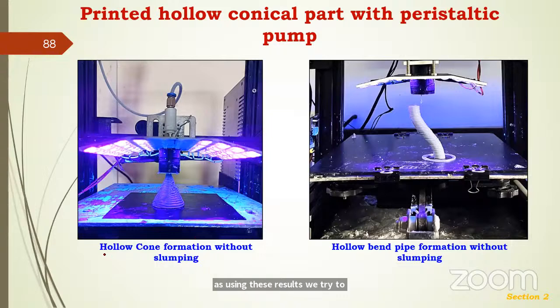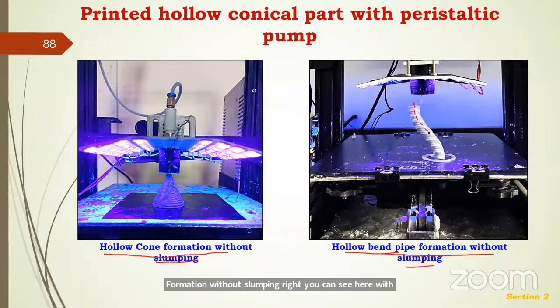So you can see a hollow cone formed without any slumping here, and interestingly, we tried to print a hollow bend pipe formation without slumping, right? You can see here, without support material, the inclination of the part we have printed through this developed setup. We didn't use any support structure here, and this concludes my presentation.